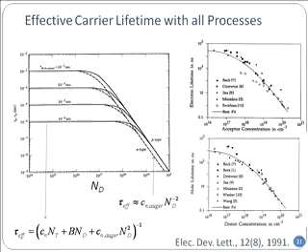And experimentally, people have seen very similar. That's the theory. So you put various values of ND and you can generate the curve. But experimentally, I have shown you from 2 different papers that indeed at high density, this is 10 to the power 20, very high density, right? 1 atom in every 100 host atoms, you can see how the values are falling off.